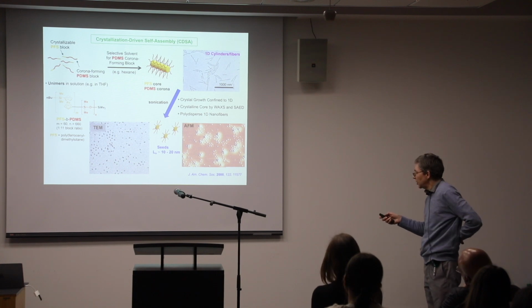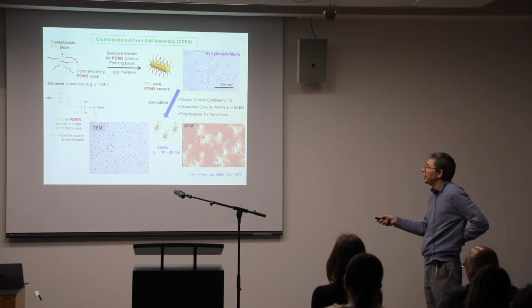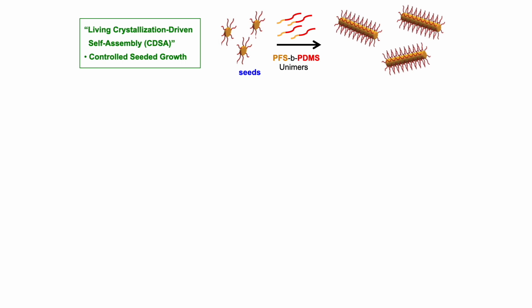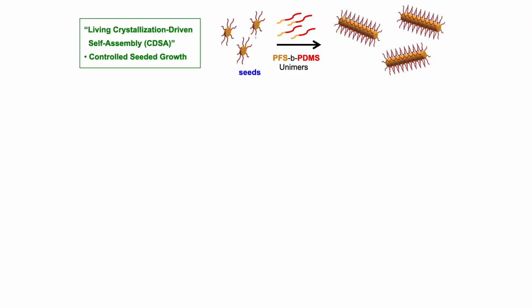Once you've got these seeds, you can take them and add more polymer to the seeds. What's remarkable is the polymer grows from the seeds in controlled growth. Each seed acts as an initiator for the growth of fibers, and each seed gives you one fiber. So if you control the ratio of polymer you add to the seeds, you can control the length of the fibers.